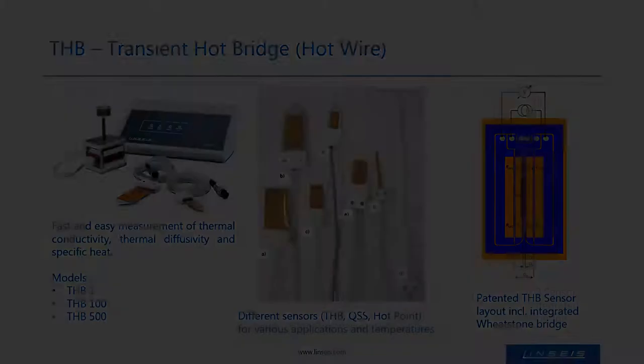The second technique presented today is the hot wire technique. Based on this, Linseis developed in cooperation with the German PTB the so-called THB — the transient hot bridge setup — which is a thermal conductivity analyzer using exchangeable sensors. The main advantages are that it is very easy to use, can directly measure thermal conductivity, and has a broad application range in terms of materials and thermal conductivity. It can be used for solids, powders and liquids, and from low-conductive to medium and higher-conductive samples. The conductivity range depends on the model and ranges from about 0.1 to up to 500 Watts per meter Kelvin. The THB comes with fully integrated software, uses only a small amount of lab space, and can be upgraded with various accessories.